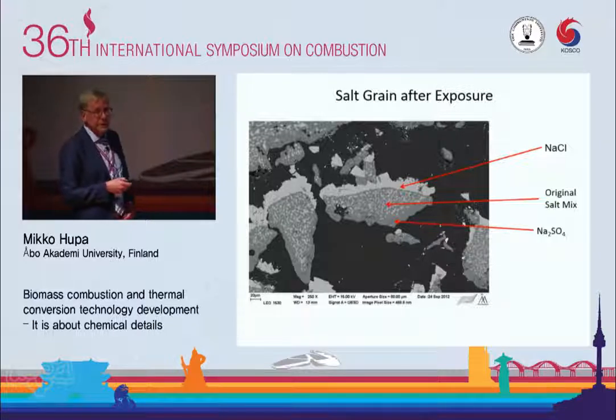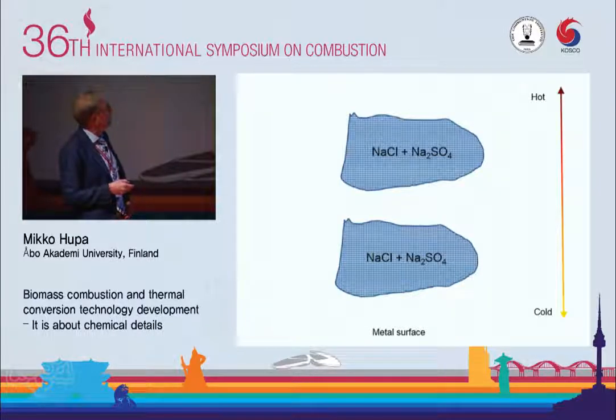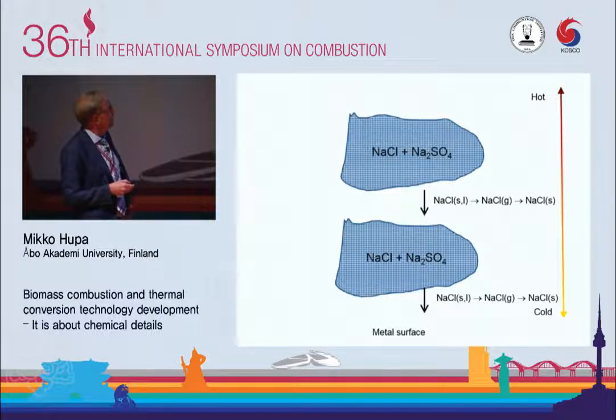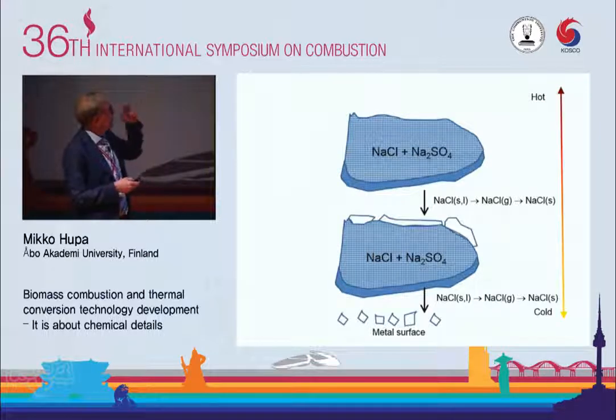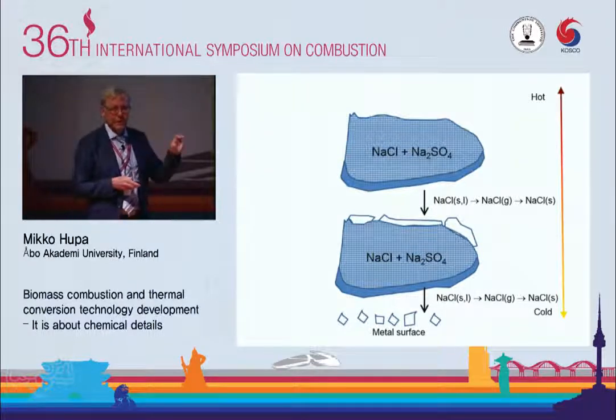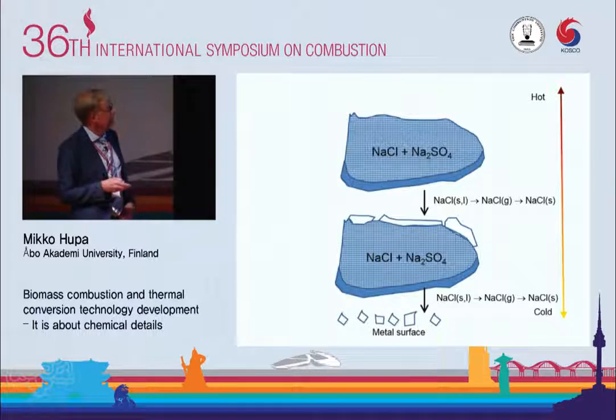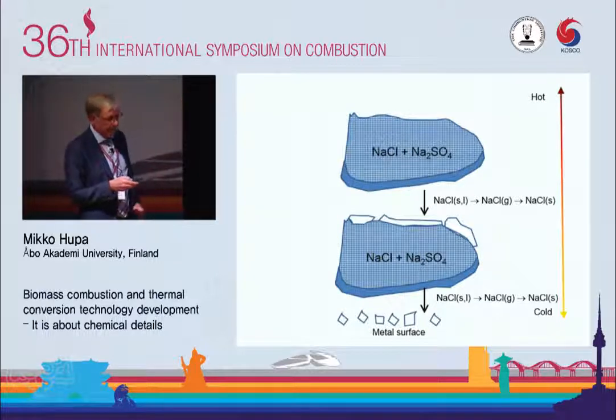And now today we think that we understand that quite well. So if the cold is down, hot is up, this is the way it goes. Simply sodium chloride starts vaporizing and is removed from the lower parts of the particles, and then it hits the next particle. And the interesting thing is that the driving force here is an extremely small temperature difference. These are small particles, 100 micrometers, but it's sufficient to transport material.